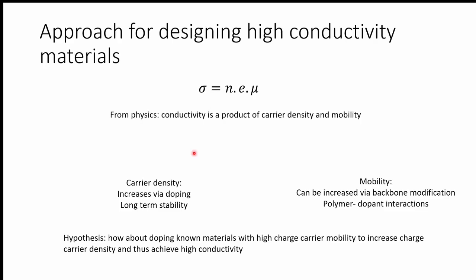Now, the other challenge is actually to have those charge carriers stay where you want them to be. And that can happen through one thing. If you get an electron transfer, you want it to stay on the polymer. You don't want the reverse reaction to just happen very easily and then for everything to get dedoped within minutes. And this is a challenge for electron transport materials because they get oxidized just by being exposed to air. So you always have to work under inert atmosphere.